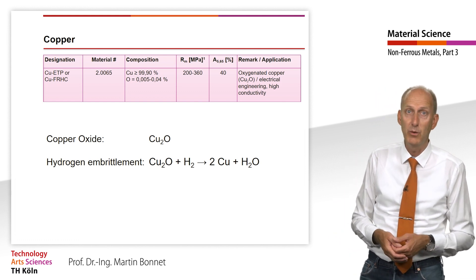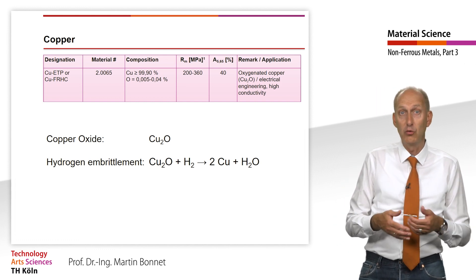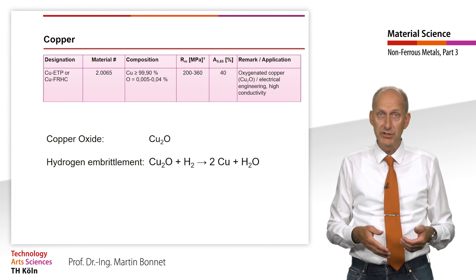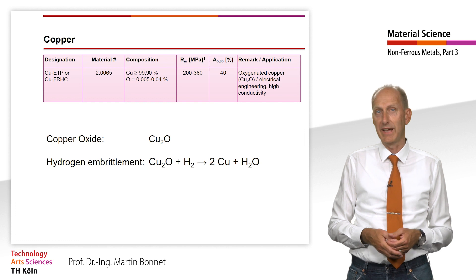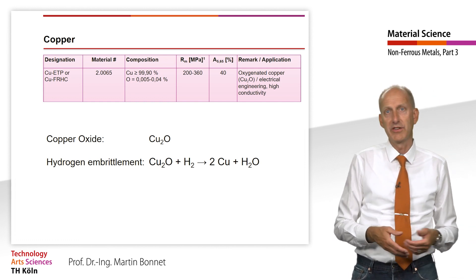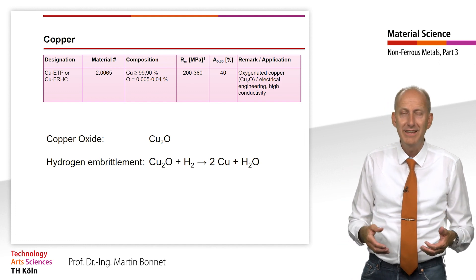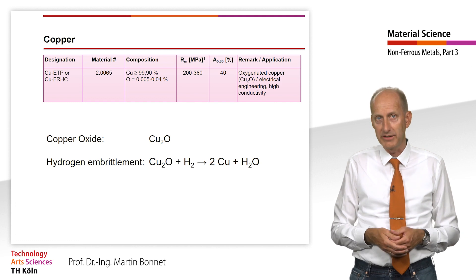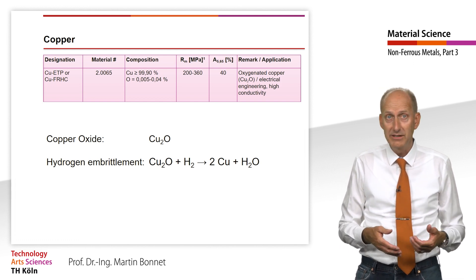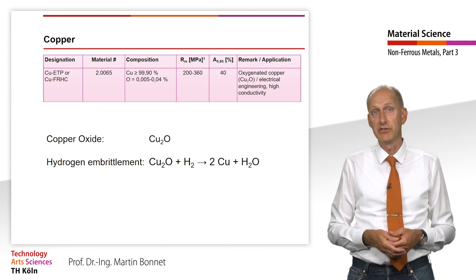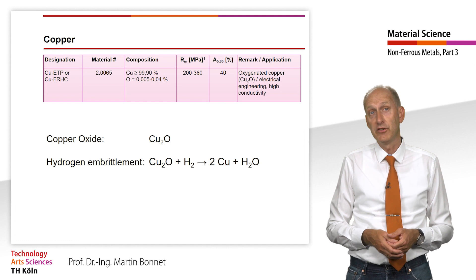As soon as such material is processed by welding, there are big problems. With oxygen-containing copper, there is a risk of so-called hydrogen embrittlement. Hydrogen is very soluble in copper in the atomic state and can diffuse into the copper lattice from welding or shielding gases. If the hydrogen atoms reach the copper oxide, they react together to form copper and water vapor. Since the water vapor cannot escape, internal pressures of several thousand bar are generated. With the low strength of copper, internal separations occur along the grain boundaries, so the copper loses its strength and above all its toughness, becoming brittle. Unfortunately, this process is irreversible.